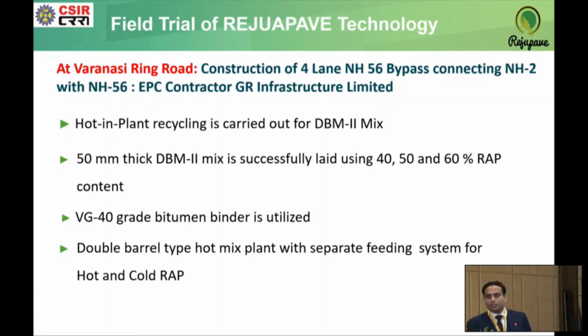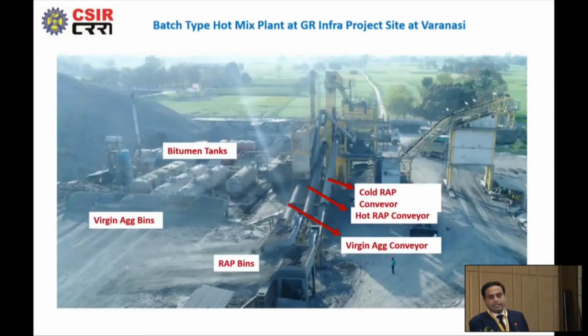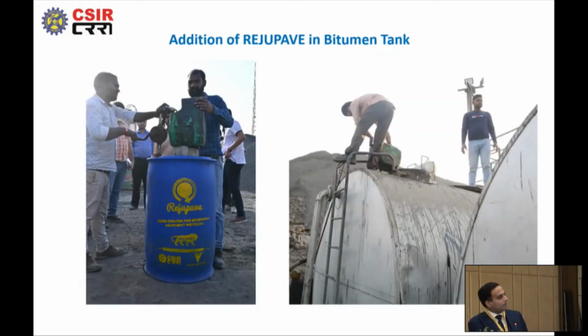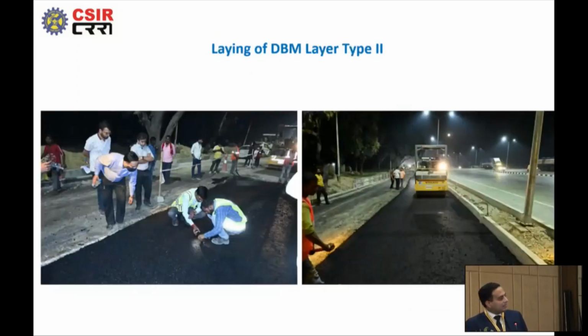The first project is the Varanasi ring road project with GR Infra. Here we utilized this Marini hot mix recycling plant, and we utilized the RAP in the tune of 40, 50 and 60%. So this is a glimpse of the Marini plant. The RejuPave rejuvenator was directly added into the bitumen tank. Subsequently, we laid the surface, and the laying temperature was around 105 to 110 degrees centigrade. This particular site was around two and a half hours far from the hot mix plant location.